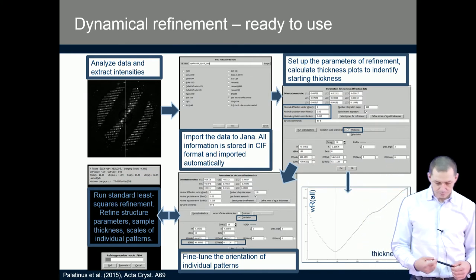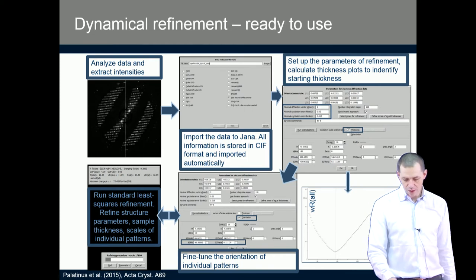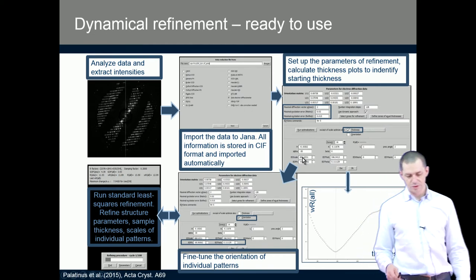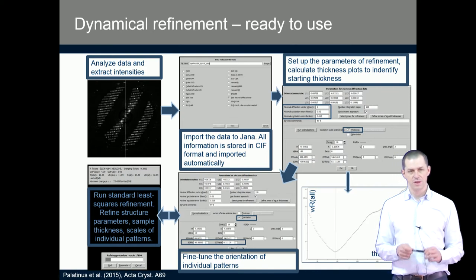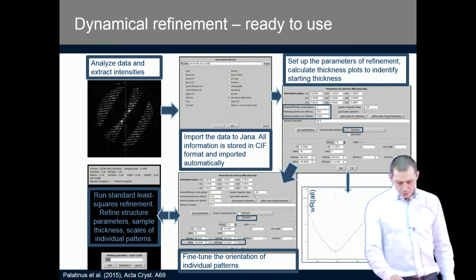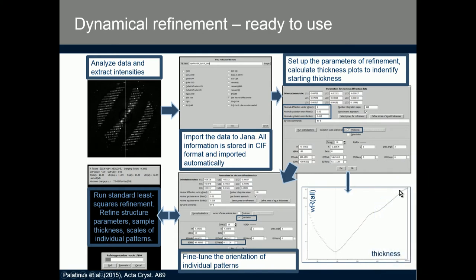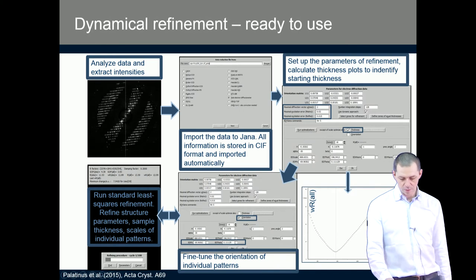So if you process the data with PETS, it prepares files that you can directly read in Jana. So then you import the data, and then you have a form that allows you to specify certain parameters unique for electron diffraction. You can calculate the R-value curves as a function of thickness. So this is an example of a nice curve that shows the R-value as a function of the thickness of the crystal, and you see a nice minimum at certain crystal thickness. Not all curves look as nice as this one, but in general, if you have a good crystal and good data, there is a trend for a minimum in the R-values as a function of thickness.